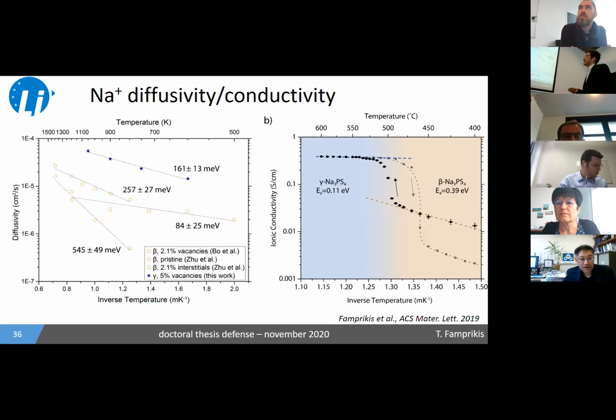So from the molecular dynamics, we can also extract the diffusivity of the sodium ions, shown here on the left through the blue stars, which has a very low activation energy and distinctly higher diffusivity than all the previous simulations in the literature of the beta structure. And this conclusion is also consistent with what we measured experimentally through impedance spectroscopy. You can see on the right. As we heat up to about 500 C, we get a stepwise increase in conductivity, a flattening of the activation energy.